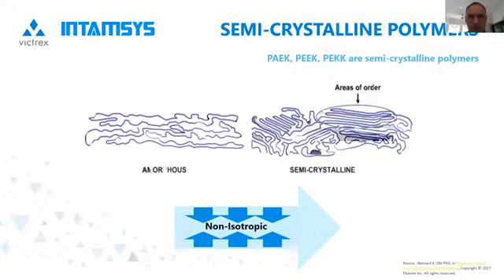And of course, the degree of crystallinity can affect the properties as well. So for example, PEEK with the structure, as I said, like on the right, is typically 30% crystalline. And this is what gives it its great properties, such as good strength and wear and chemical resistance. So different PAEK family members can have different crystallinities, or the same family member can even have different crystallinities depending on temperatures that you expose them to. So for example, PEKK can have amorphous or crystalline grades available. So some applications you get asked for may be more than covered by the end properties of an amorphous version, if the demands of temperature or chemical resistance are lower, for example. And typically amorphous versions print more readily.